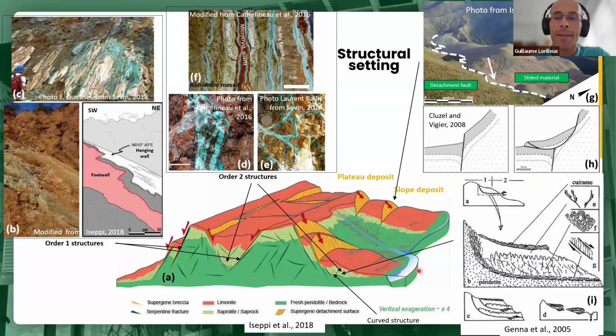This is a synthetic 3D drawing summarizing the structural setting of plateau and slope deposits, with all the order 1 structures represented here, controlling the deepening of the weathering and the geometry of the nickel traps, and all the order 2 structures developed within the weathered volumes, so inside here, for example, controlling nickel enrichments. And gravity faults, for example here, associated with slope deposits and responsible for further nickel enrichments, as we saw in the previous slide.